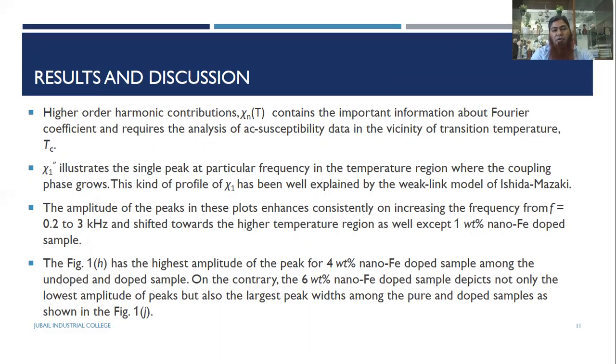And also the amplitude of the peaks in these plots enhances consistently on increasing the frequency from 0.2 to 3 kilohertz. And all these peaks are shifted toward the higher temperature region as the temperature goes down, except the 1% nano iron doped sample, which is showing different behavior.